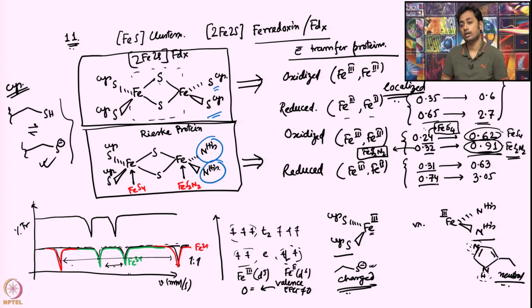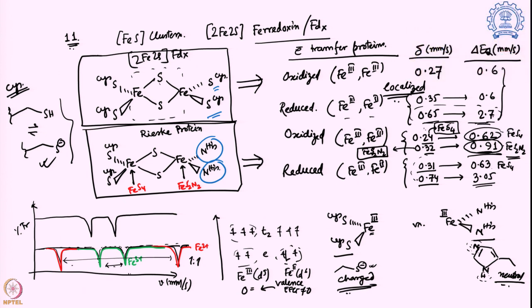Now which one can I actually confer, like it is actually the N2S2 or S4? So you can see the splitting and the value is remaining almost the same for this iron 3 for this FeS4 system. But this one, 0.32, is split to 3.05, much wider, even wider than what we expect for the normal 2 iron 2 sulfur ferredoxin where all of them are sulfur. Even then it is going beyond that. So that is actually coming because of the asymmetry related to Fe(S2N2).